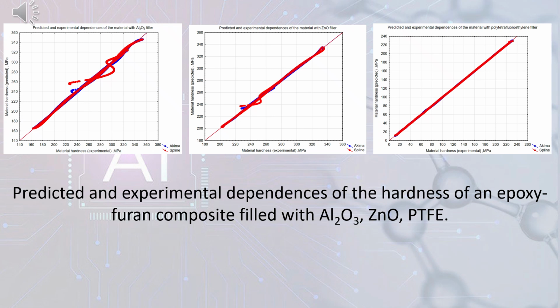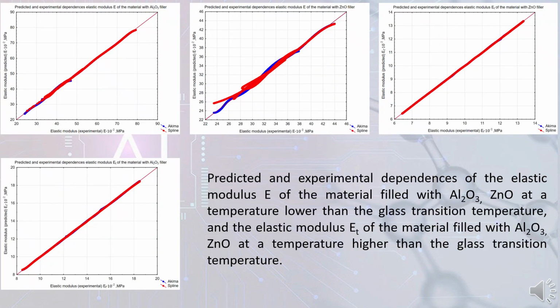A comparative analysis of different neural network architectures is performed, choosing the optimal parameters and training algorithm that minimize forecasting error. The stability, accuracy, and reliability of the model are improved, which is a prerequisite for its application in real-world problems, in particular in predicting the characteristics of composite materials. Here we see the prediction of the experimental dependence of the elastic modulus E of the material filled with aluminum oxide and zinc oxide at a temperature lower than the glass transition temperature, and the elastic modulus of the material filled with aluminum oxide and zinc oxide at a temperature higher than the glass transition temperature.